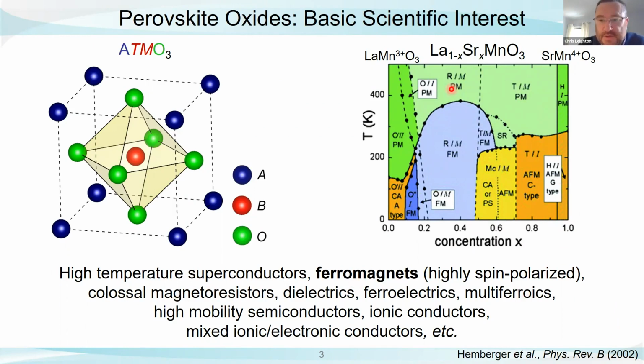So as an example, what I show here in the top right is one of the best understood magnetic perovskites. It's lanthanum strontium manganite, or LSMO. I show you its phase diagram. So this is temperature as a function of substitution of strontium for lanthanum. And what's happening basically in this phase diagram is on the left side, because lanthanum is trivalent, we have manganese 3+. On the right side, because strontium is divalent, we have manganese 4+. So as we dope one hole per unit cell to traverse this phase diagram, the point is that there are about half a dozen different electronic and magnetic ground states.